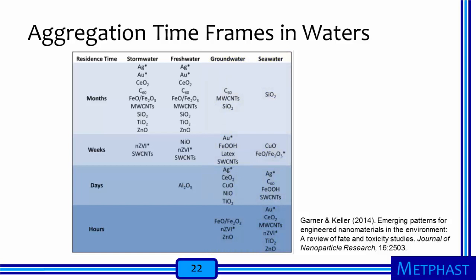Zinc oxide nanoparticles, and especially zero-valent iron nanoparticles, are among the engineered nanomaterials most likely to aggregate quickly in many or all of the aquatic systems. Although aluminum oxide nanoparticles were only tested in freshwater, it was the engineered nanomaterial that aggregated most readily in that system. Nanosilica is slow to form aggregates in all of the aquatic systems. Other nanomaterials vary across the different types of water.